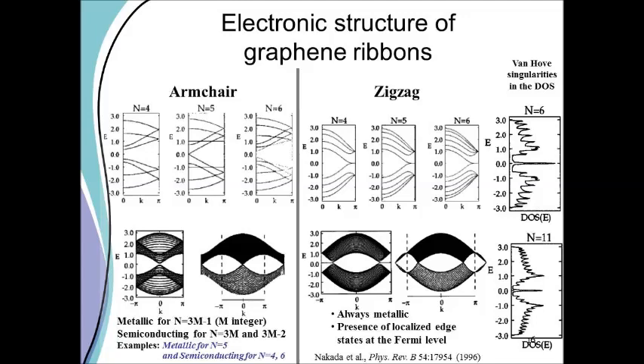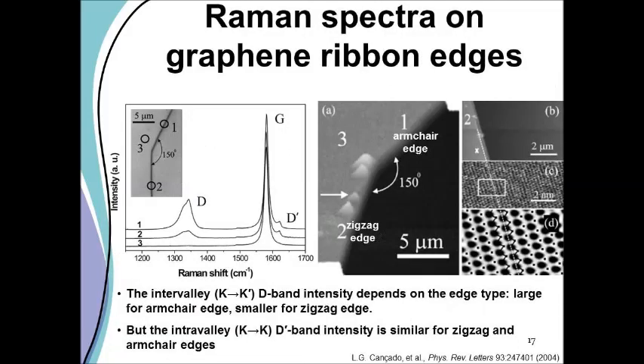And so we did Raman spectra, and you can distinguish when you're on an armchair edge and when you're on a zigzag edge. So this is done now with Raman, and here it is with a scanning probe method. You can see which edge you have, just by atomic position. And this is with what the phonons are doing. So the spectra look different, and so we can tell which edge we're looking at.